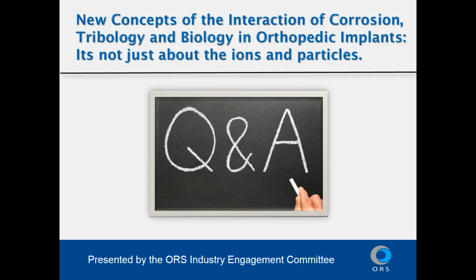And then the inflammatory cells can also induce corrosion. So you can have either happening in isolation or you can have them happening in combination. And I think it is such a coupled interaction that it's very difficult to separate out which is which. Now, it may be that we have high levels of mechanically assisted corrosion, which tends to be observed in implant retrievals, but relatively low percentages of revisions associated with, say, trunnion corrosion type symptoms.